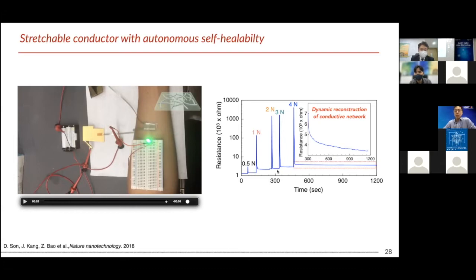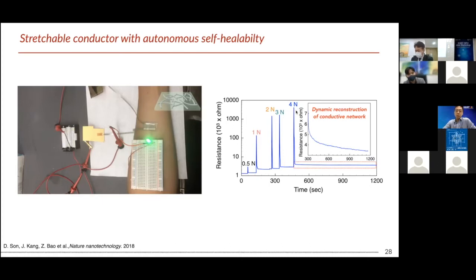To fully investigate what's happening here, we perform a more quantitative analysis. So we measure the forces of the scratching. We increase up to 4 Newton. After removing the razor blade, you can see a very rapid recovery of the resistance at this first step. So it is more related to the physical contact between the damaged surfaces. But the more important thing is that over time, you can see a significant resistance decrease, meaning that they are continuously reconstructing their nano network and restoring their electrical properties.